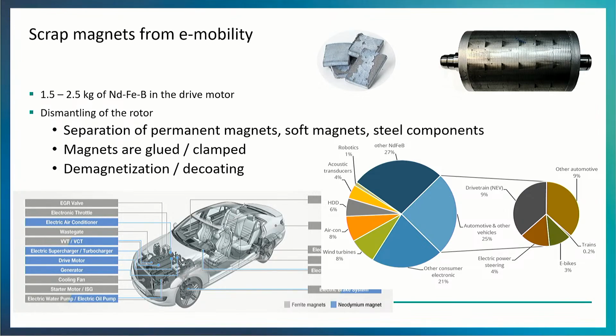We find in a normal car, like in a Tesla, around 2.5 kilograms of these materials. To recover it, we have to dismantle the motor completely, and this is hard because it is magnetic. You have to demagnetize it beforehand. And it is also glued and clamped, a very tedious procedure. So until now, no one is really doing this. We developed a method where we can directly embrittle the material inside the motor with hydrogen so that we can recover it in a more sustainable and more energy-safe way.